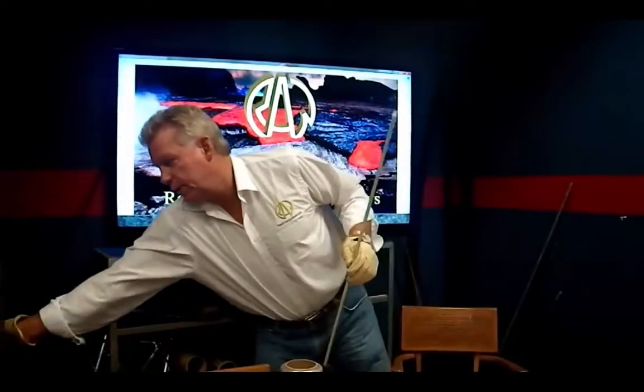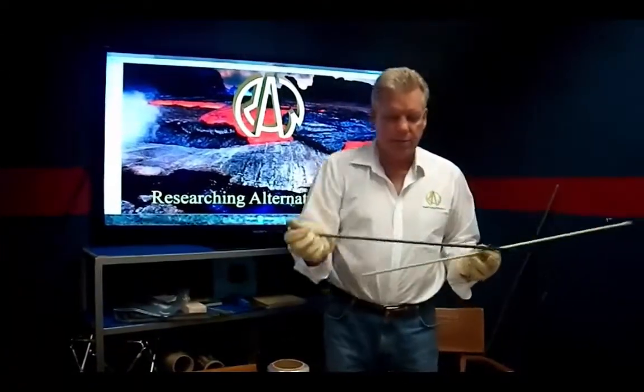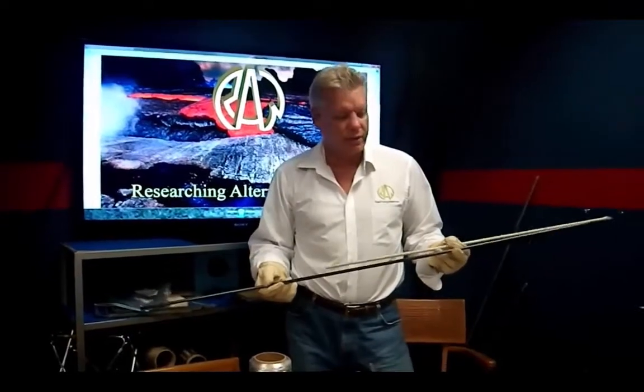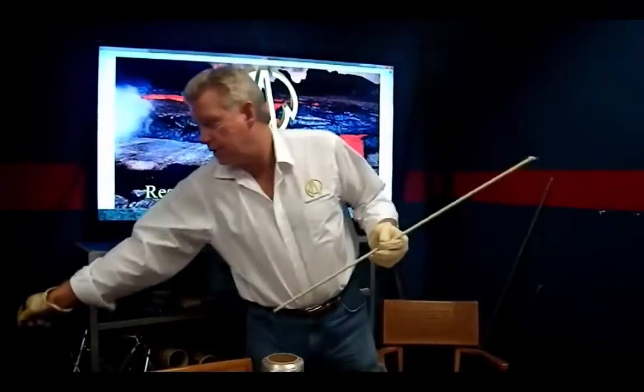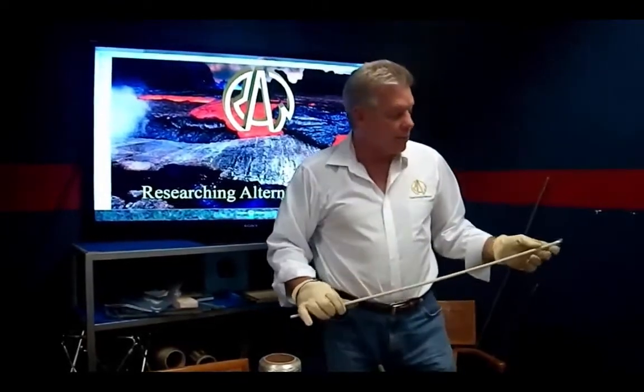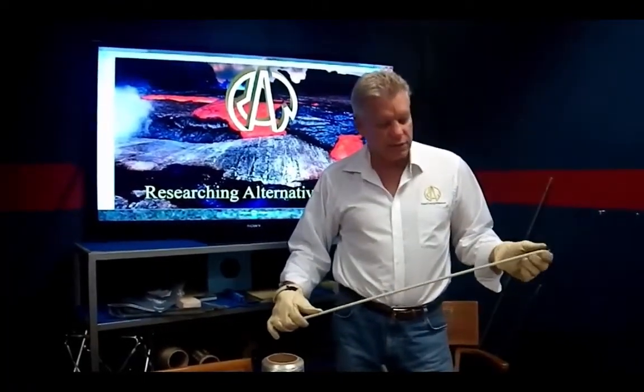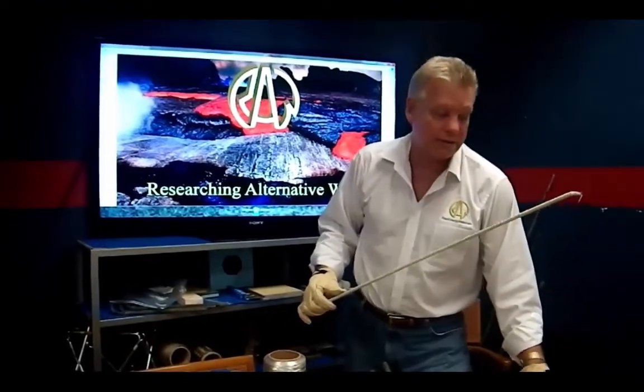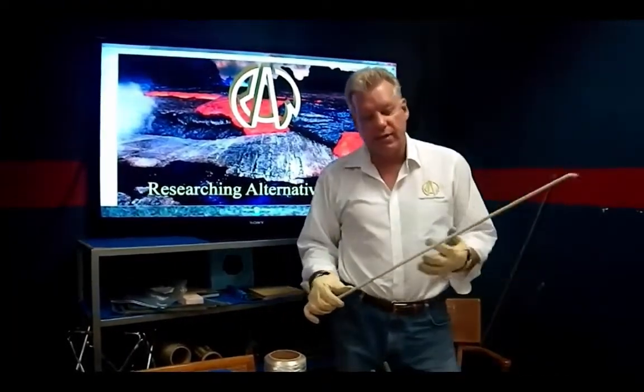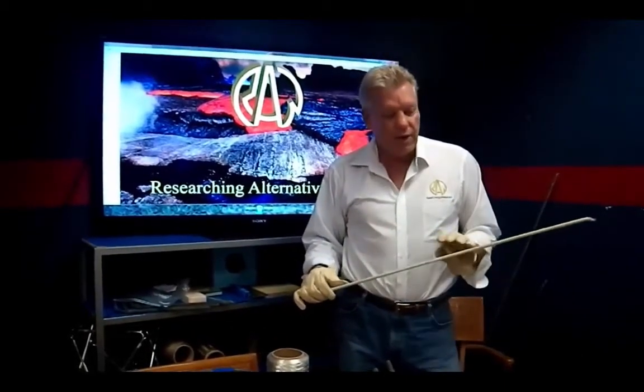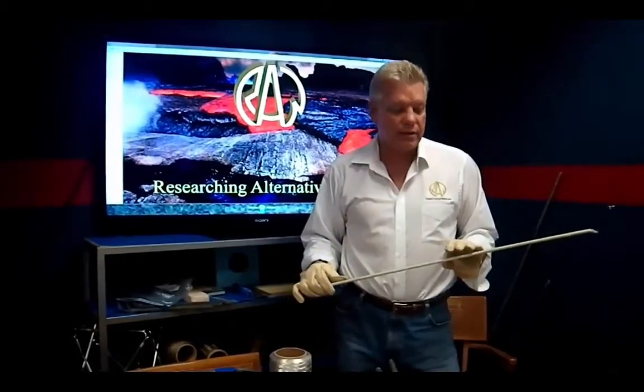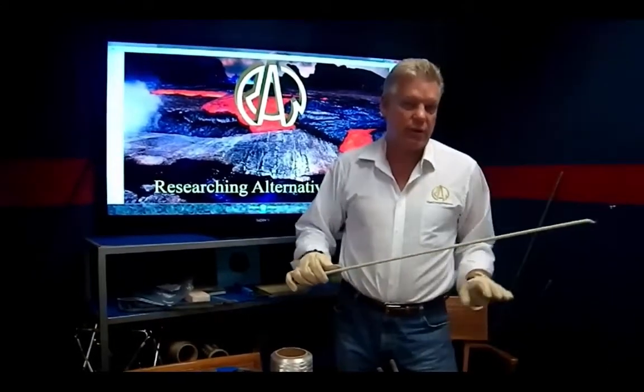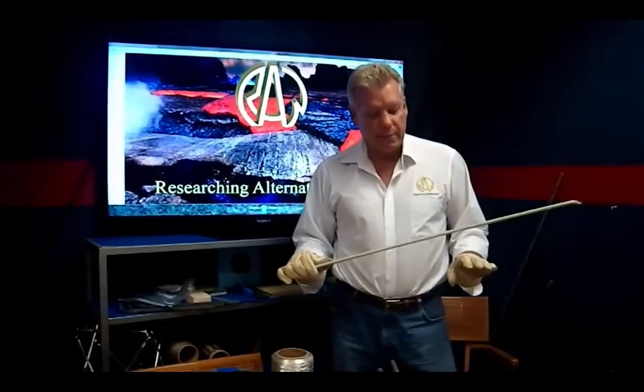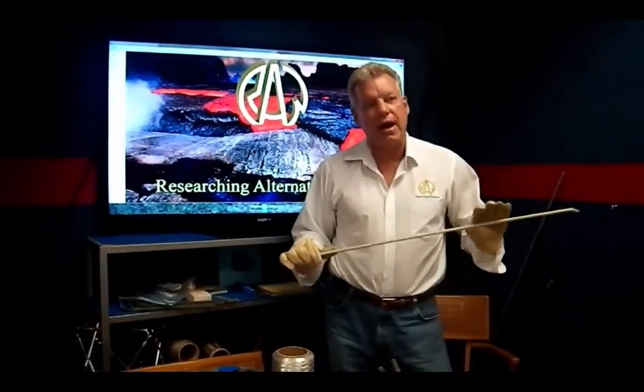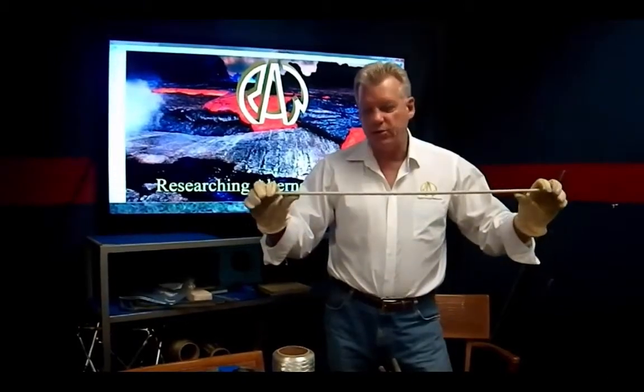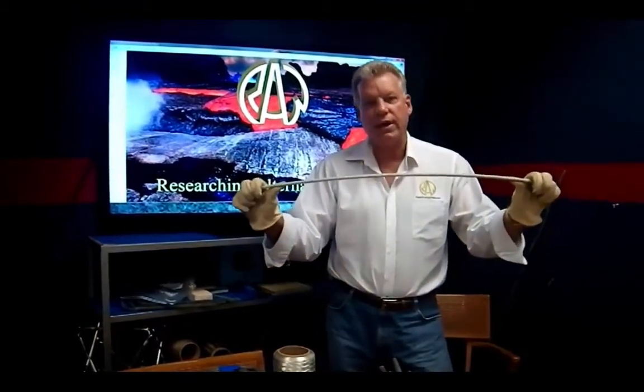We've got a piece of carbon fiber over here, really expensive, 20 to 30 times more expensive than fiberglass, and of course much more than steel. Fiberglass has a tensile strength of actually more than twice what steel has. Steel is 60, fiberglass is 120. Where fiberglass is potentially a little bit weak is in modulus. Steel has a modulus of 200 gigapascals. Fiberglass about 50. And you can demonstrate that in that fiberglass is quite flexible.